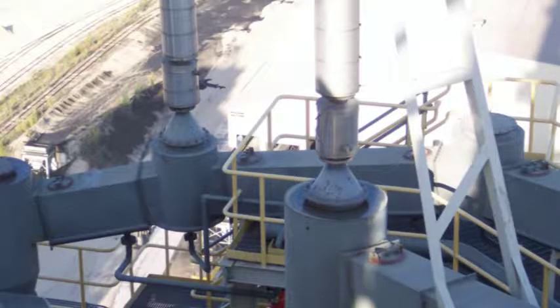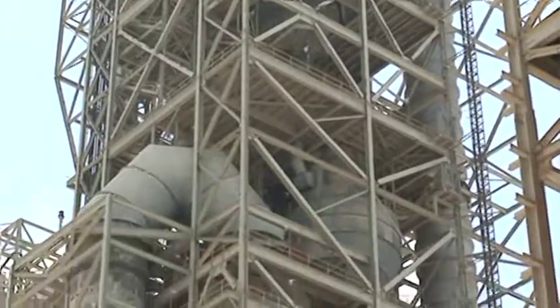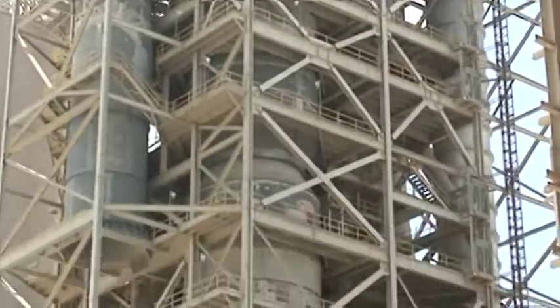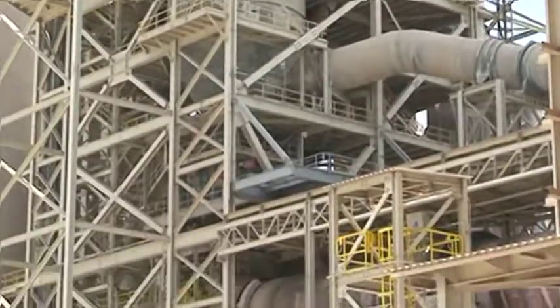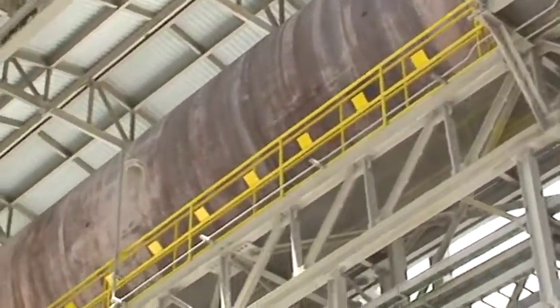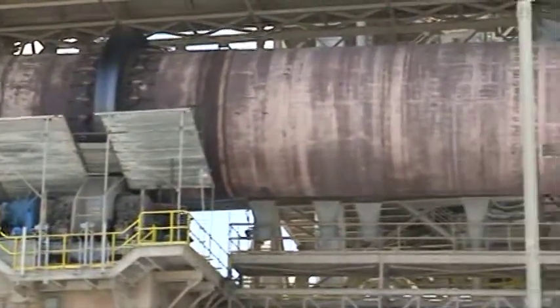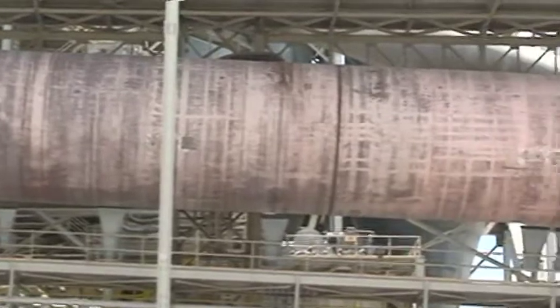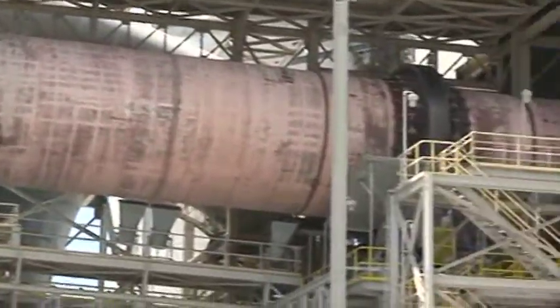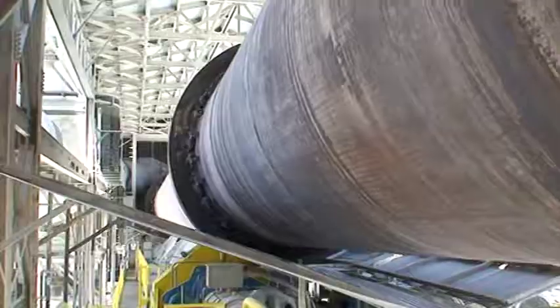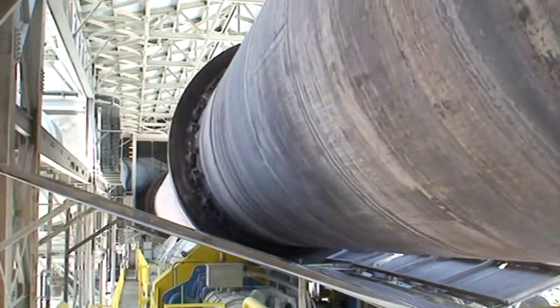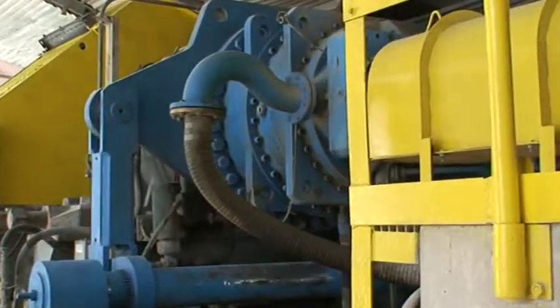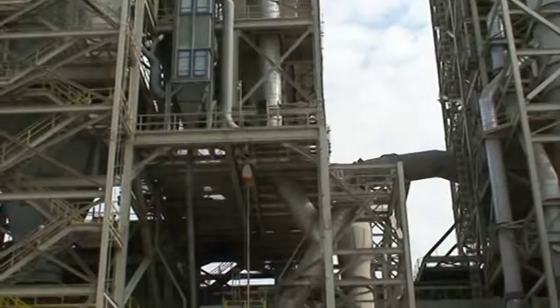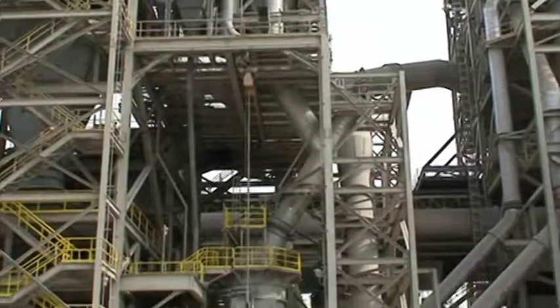In its 25-second drop from the top of the tower, the material temperature rises from 170 degrees Fahrenheit to 1600 degrees by the time it enters the kiln. The calcined feed enters the kiln that is 65 meters in length and 5 meters in diameter. In approximately 20 minutes, the material temperature will go from 1600 degrees to 2400 degrees by the time it exits the kiln as clinker. Pulverized coal is used as the main fuel source.